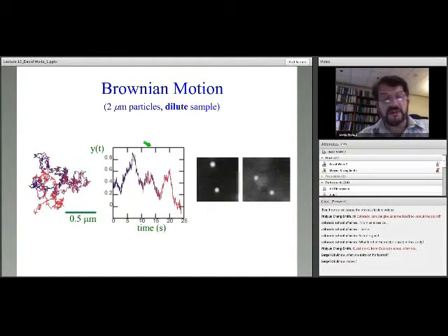This only works, of course, if you have particles that are well separated, so that you can identify the centers. You can't do this if you have to deconvolve a group of particles and you don't even know how many particles you're looking at. However, for all systems that we typically look at with colloids, the particles are spherical, and it's very easy to identify the center, and then you can locate the position of the particle very easily to, say, 10 or 20 nanometers.